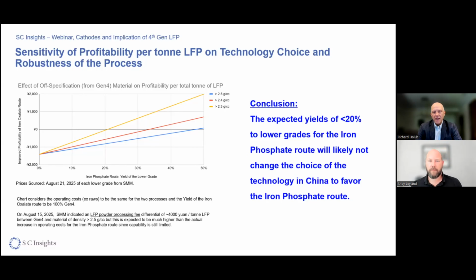As I said, this was assuming that everything other than the raw material costs is the same. That's not necessarily true. The iron phosphate route does have an additional sintering step and higher costs, but an indicator of that is this LFP powder processing fee that's also available on SMM. The differential between Gen 4 and the Gen 2.5, if you will, was about 4,000 renminbi per ton. That would include profitability as well as the difference in production costs that we expect because of the second sintering step. Right now the availability of people to process Gen 4 seems to be very limited in China, so I'd expect that 4,000 to include quite a bit of profit in a market shortage for processing. So the difference in cost is going to be less than 4,000 renminbi per ton, is the point I'm making.